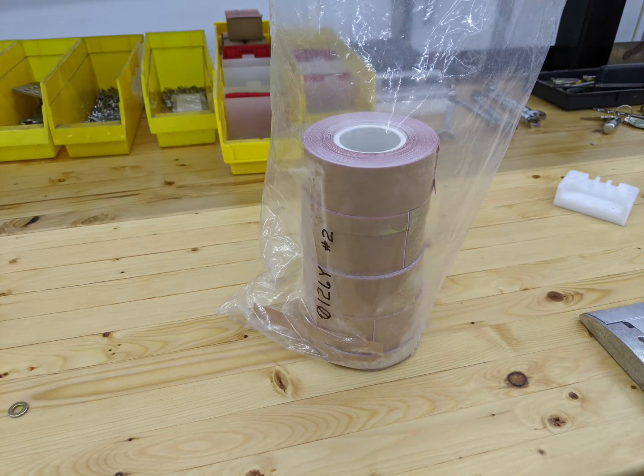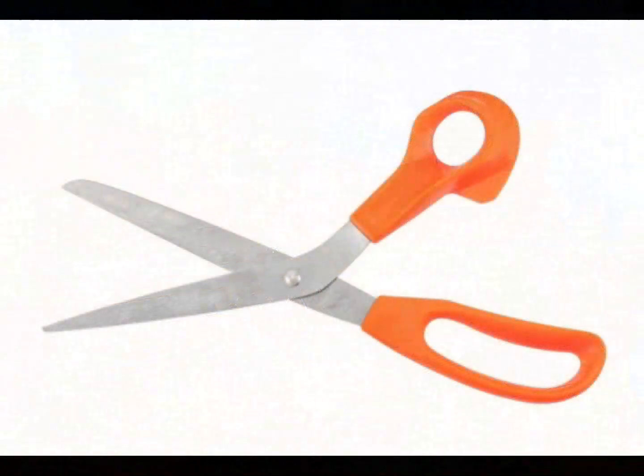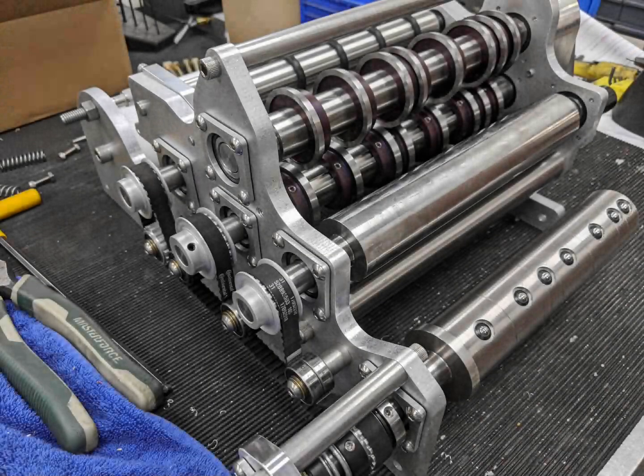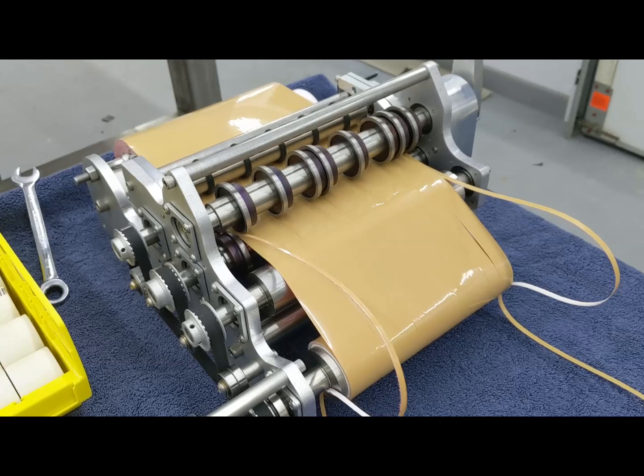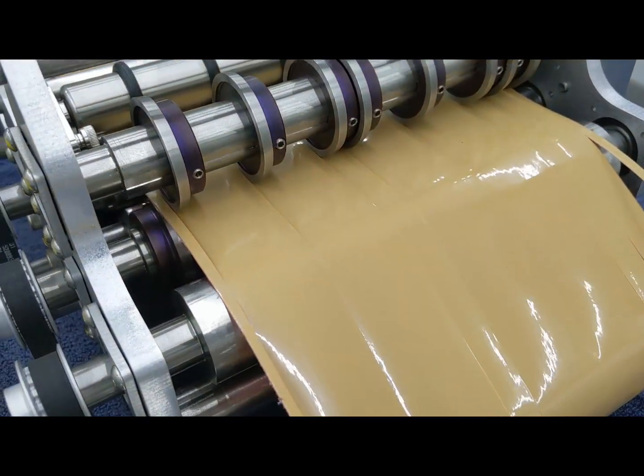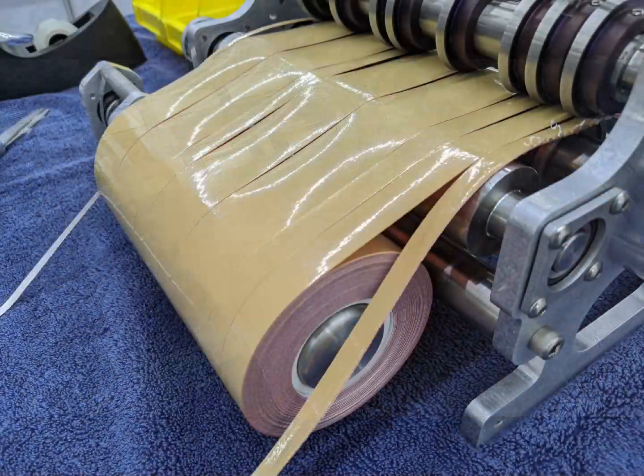The adhesive comes on a wide roll and needs to be converted into smaller strips for the blade assembly. It's removed from the freezer and allowed to thaw and slowly acclimate to room temperature so as not to impose any condensation on the material once it's removed from its sealed packaging. I tried several ways to cut it down to size, all of which turned out to be slow, made rough edges, and were just not very accurate in general. So we designed and built our own conversion and slitting system just for this process. Now we get smooth, repeatable cuts exactly the width we need to use on the blades.